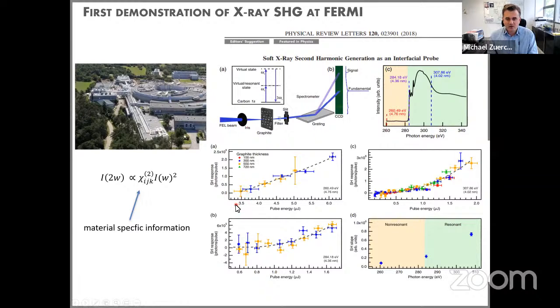What I want to point out here in this first work, and that's what really caught my imagination back then about what would be possible with this method, is that what you can see here is the second harmonic response measured for different thicknesses of this graphite film. The researchers in this work used 100 nanometer up to 700 nanometer thin films of graphite. And what they see is that for all the different thicknesses, the response remains the same. So what this tells us is that indeed this is a surface sensitive measurement. It doesn't matter how thick your crystal is, you see the same response, because all you get is essentially the surface response of the system. So that was the first reassurance that first of all, you can do second harmonic spectroscopy in the XUV, and indeed you get access to the surface.